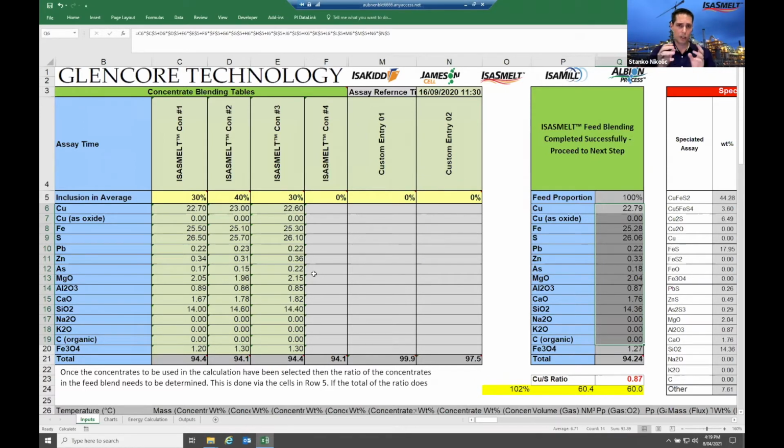And then you look at those smelters, and they do find it difficult to treat high lead, zinc, and arsenic feeds. And that's where the ISASMELT really comes into its own, in being able to assist clients to process these concentrates, which might have high lead, zinc, and arsenic, and then push that to the fume, and recover that through a dust leaching process, like a modified Albion process technology for dust leaching, which is done at Mount Isa Mines in the Glencore group. And you're then able to maximize the value that you get from treating these kinds of concentrates.